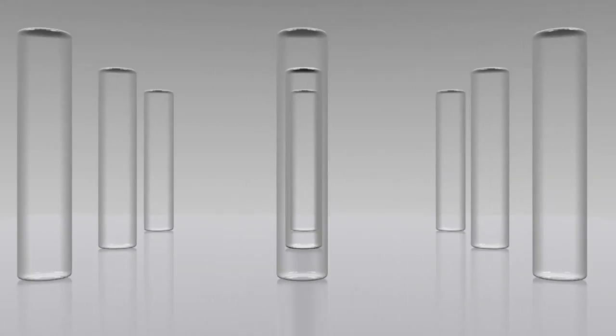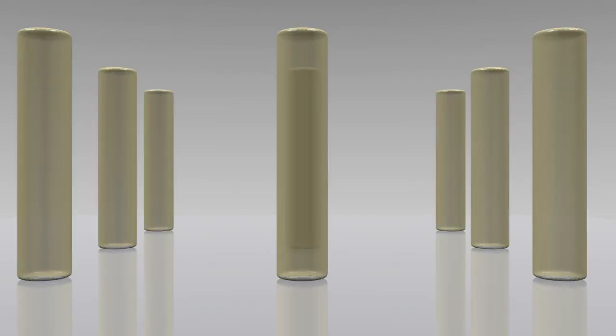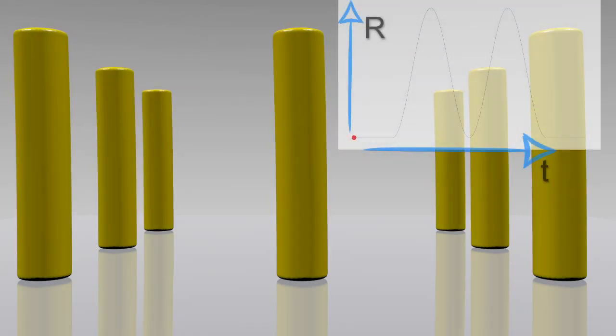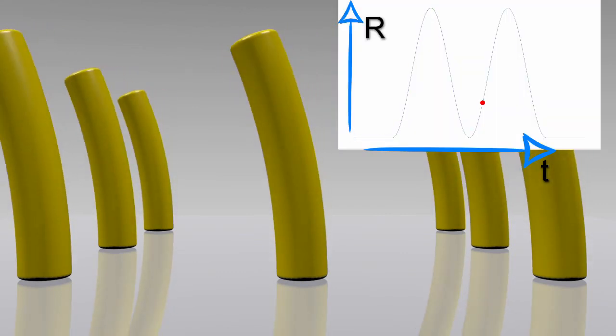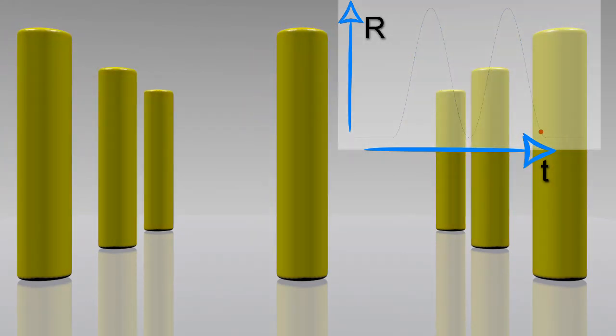Now, I'm going to explain the cilium sensor working mechanism, and although PDMS is transparent, to better observe the pillars, I'll make them golden. So, if the pillar's magnetization direction is vertical, then when a force is applied, the pillars bend, and the direction and magnitude of the average magnetic field over the sensor changes, inducing a change in resistivity.